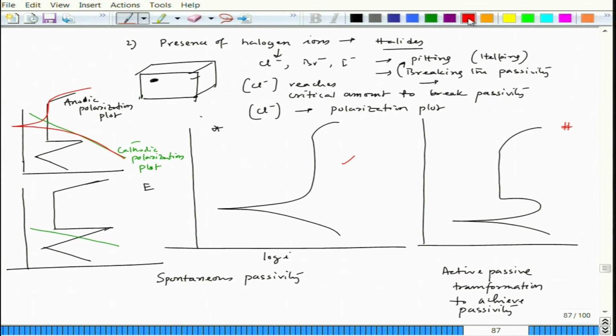So, now if I try to see the plot nature, it will look like this. So, you see this is exactly like this. This is the interaction between cathodic and anodic plots while considering mixed potential theory, and you can achieve this kind of lines. Now, this point where a sharp break happens is in the passive region. So, you can see that this is the passive region here also. This is the part where the passive film has grown.